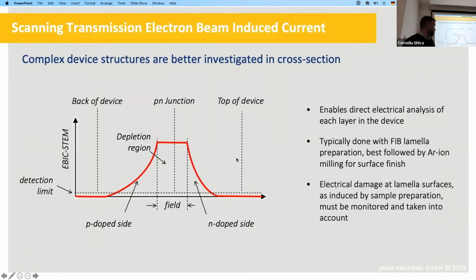In cross-section, and TEM tends to be cross-section of thin lamellas, we will have a relatively constant signal in the middle of the junction, so where the built-in field is, and we can change the width of this field by applying a bias, reverse bias to widen it, forward bias to narrow it. That's the in situ part of the work. And then we have diffuse edges on either side. And again, we would be looking at how fast these edges are decaying to see what the diffusion length is.